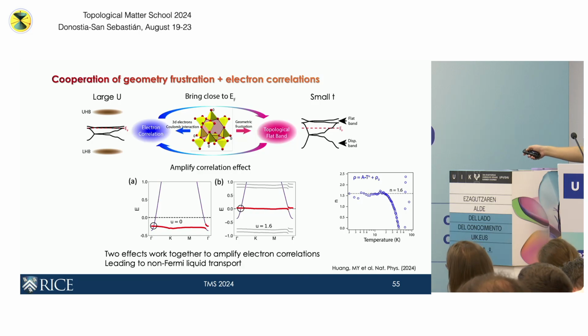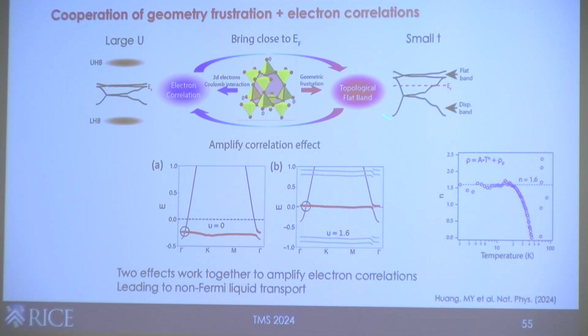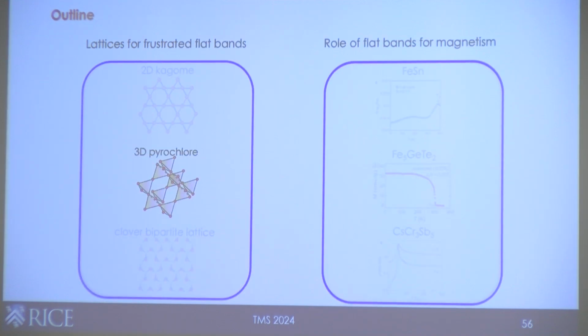One is that, first of all, you have the pyrochlore lattice that gave you the destructive interference to produce the flat bands. And then in addition, there are moderate electron correlation effects that further push the flat bands towards the Fermi level to eventually give us this phenomenon. So these two effects go hand in hand to give us this flat band near the Fermi level in bulk. And then, from resistivity measurements, we can see that there's a power law which is deviating from n equals 2. It's not quite T linear, but it's at least deviating from T squared, as we heard from the last talk, in Ira's talk. Okay, so that's the second example.